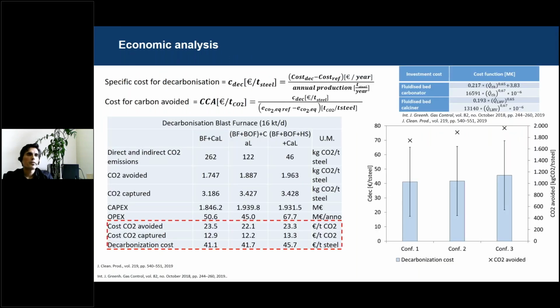configuration. With regard to the economic analysis, we have also considered the specific cost for decarbonization, which is the ratio between the increase in the cost of the total plants and the annual production in terms of tons of steel per year. And we have also evaluated the cost of carbon avoided, which is the ratio of this value to the carbon avoided. As you can see here, thanks to this good integration between the CaL, calcium looping process, and the steel mill, we have a cost of CO2 avoided of approximately 23 euro per ton, whereas the decarbonization cost is more than 40 euro per ton of steel. The biggest is for the most integrated one.